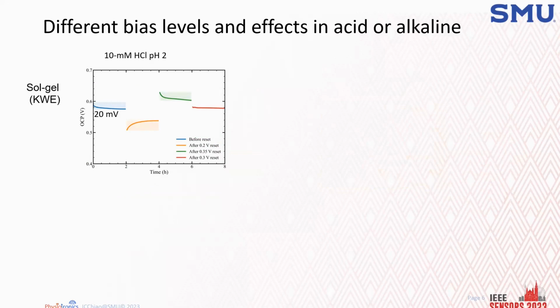For a sol-gel, we started with a fresh electrode, and we found out the drift is about 20 millivolts. And then after 2 hours, we set a reset voltage, 0.2 volts, and we found out that now the drift become worse, become 29.7 millivolts. And then after 2 hours, we reset again, 0.35 volts, and now we found the potential change again. And then in the end, we reset at 0.3 volts, we found the potential drift is minimized. So we know that, okay, for sol-gel in acid, we should probably use 0.3 as a reset voltage.